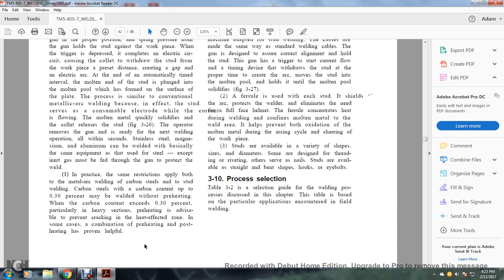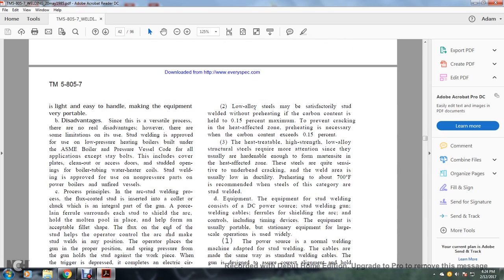In practice, the same restrictions apply to both metal arc welding of carbon steel and stud welding. Carbon steels with carbon content up to 0.30 percent may be welded without preheating. When the carbon exceeds 0.3 percent, particularly in heavy sections, preheating is advisable to prevent cracking of the heat affected zone. In some cases, a combination of preheating and post heating has proven helpful.